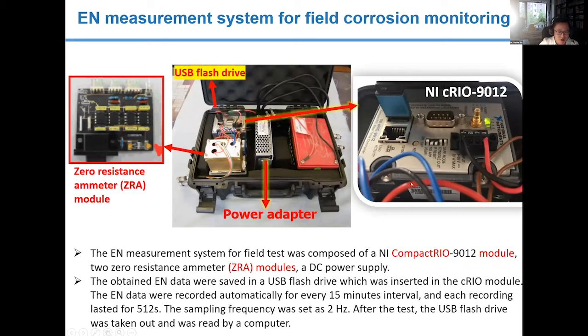It was composed of a real-time embedded controller as shown on the right, and two self-made zero resistance ammeter (ZRA) modules as shown on the left, and one DC power supply. Our experience showed that this instrument has successfully worked in outdoor conditions for 6 months. The obtained EN data was saved in a USB flash drive as shown here. The EN data were recorded automatically at 15 minute intervals, and each recording lasts for 512 seconds. The sampling frequency was set as 2 Hz. After the test, the USB flash drive was taken out and was read by a computer.